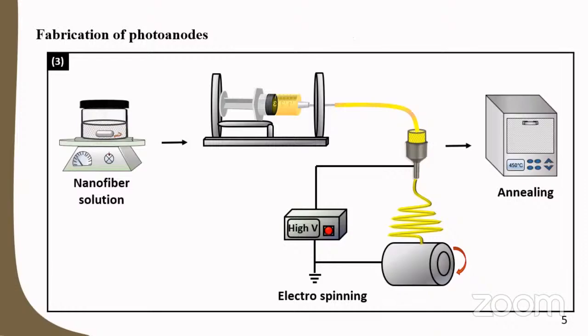On top of the TiO2 P90 layer, a TiO2 nanofiber layer was deposited. For that, a viscous solution of titanium isopropoxide was prepared by mixing with polyvinyl acetate, dimethylformamide and glacial acetic acid by magnetic stirring. A TiO2 nanofiber layer was deposited for 20 minutes with a solution flow rate of 2 ml per hour on the TiO2 P90 layer by the electrospinning technique as illustrated here. Next, the electrodes were sintered at 450 degrees Celsius for 45 minutes.